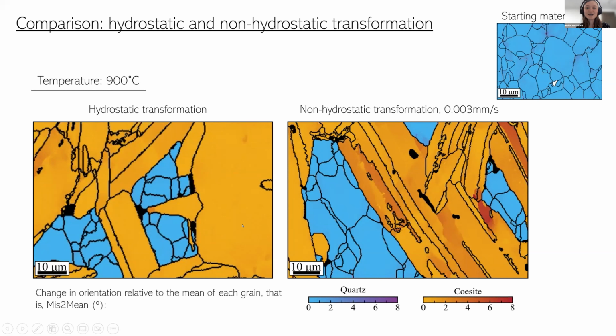So here we've got coesite in the orange, and you've got this blue. Blue is the quartz. And in the hydrostatic transformation, we haven't really got any distortion to the crystallographic structure, which is what we'd expect because we've not been deforming it. Now, if you go into the one which we are deforming, and therefore we have this transient weakening process, interestingly, what you'll notice is the quartz microstructure doesn't seem to have any deformation in it, but the coesite has quite a lot of internal misorientation.